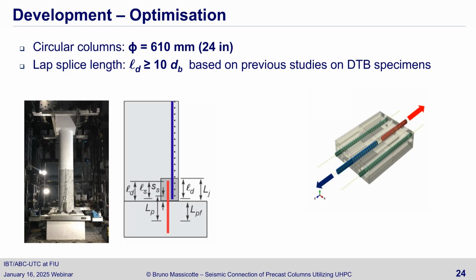I don't know if I still have control of my presentation, but if I go very quickly to a test, this test has been used. We call that DTB. We named it that way, and we're not the only ones using that test. But we made sure that we came to a standard type of specimen. This type of specimen can be cast on the site, and then in the lab later on, you can pull on the central bar here, and that bar is a bit shorter. So this is the bar that breaks. This is a test that has to be done, according to me, before you design your UHPC. It's information that has to be given by the supplier, and you cast a few of those during your construction. So this is an indirect way to test the tensile behavior of UHPC. So this is one way.